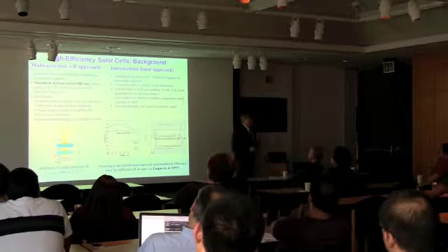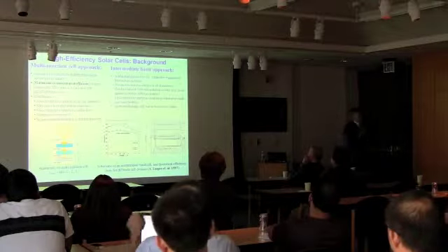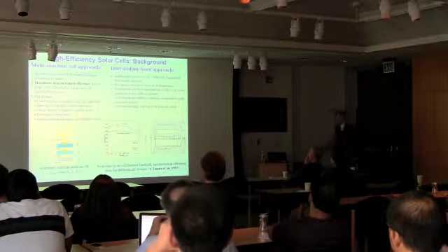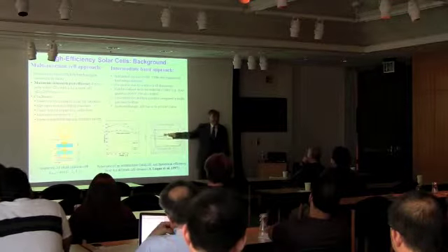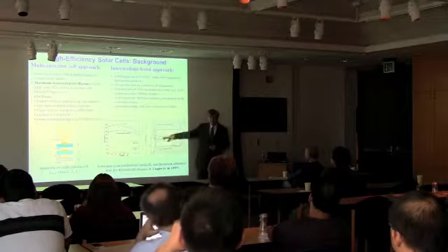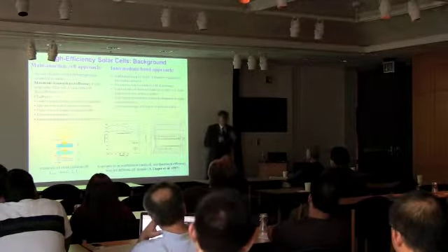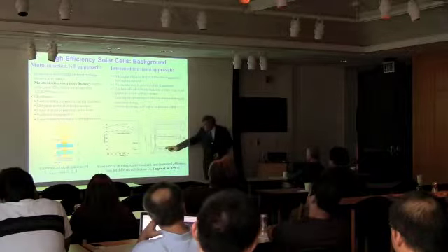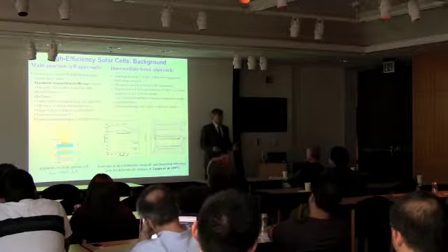What is the advantage now? They say, okay, like before, all photons that have energy larger than the band gap of the initial material will be absorbed. Now, that band, I am smart enough to make half filled. What does half filled mean? You have some electrons there, but you also have some empty states. So now, the photon that takes electrons from here and brings them there will be absorbed as well.